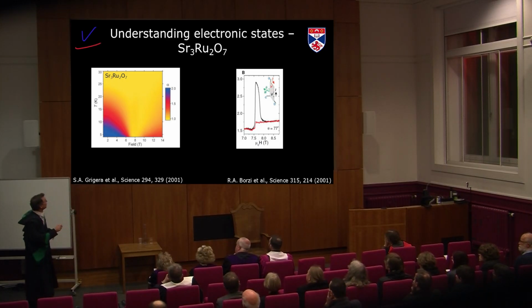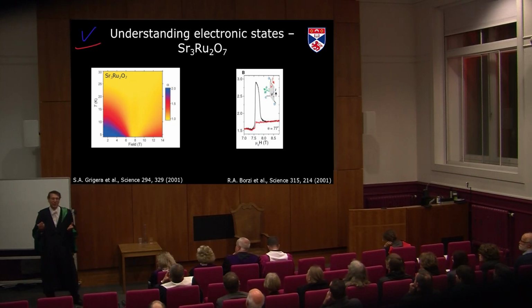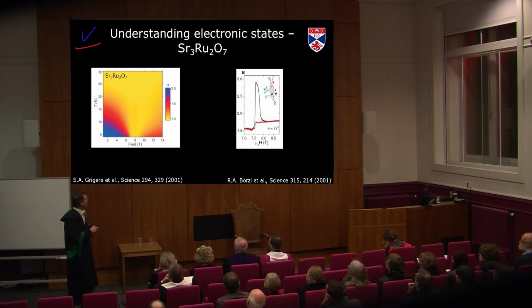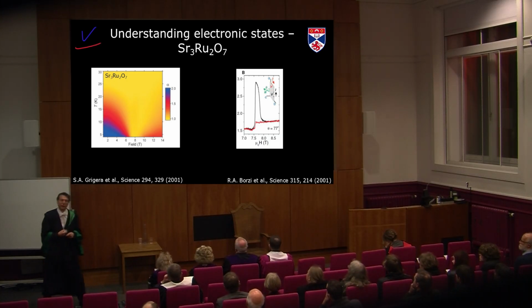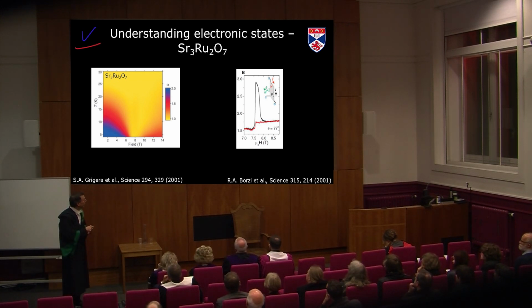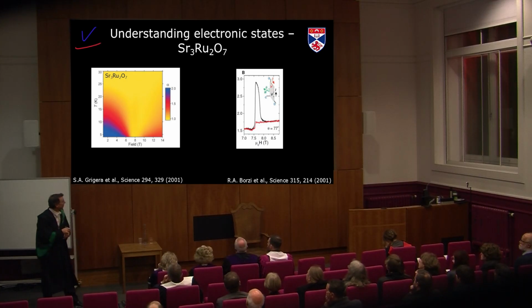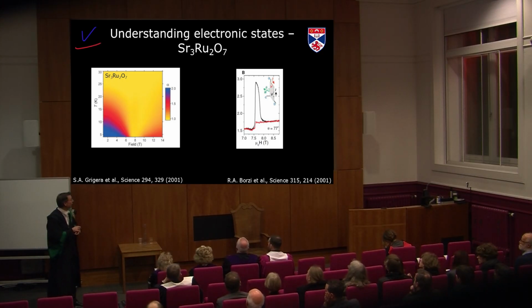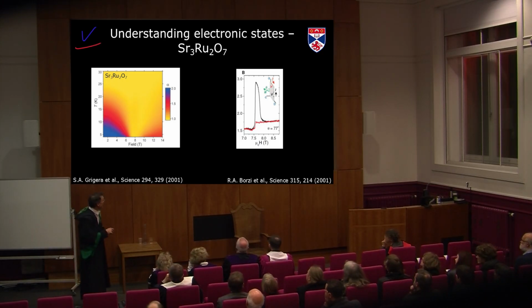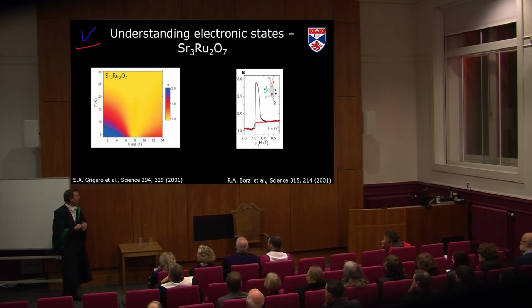They studied this material strontium ruthenate, which has this stoichiometry here, strontium ruthenate 327. And what they found is that if they apply a magnetic field to the material in a peculiar direction, then the current becomes different whether it flows in the same direction as the applied field or whether it flows in a normal direction with respect to the in-plane component of the applied field. Here, the red and the black curve are the two currents in the two orthogonal directions, and you can see one of them is low, one of them is high. Which in principle is interesting because it means you can control current with a magnetic field,